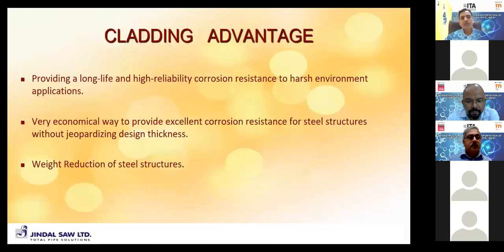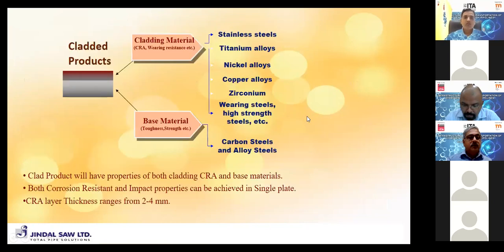Next slide, please. So, cladding advantage: we already know that a corrosion resistant material is inside the carbon steel, and it is very economical because there is less weight to use during construction. Next slide, please. So what material can be used? As I said, stainless steel can be used, like CRA, titanium alloys, nickel alloys, copper, zirconium, and the backer base material can be carbon steel or alloy steel. Normally the CRA layer would be 2 to 4 millimeter depending upon the design of the pipeline. Next, please.